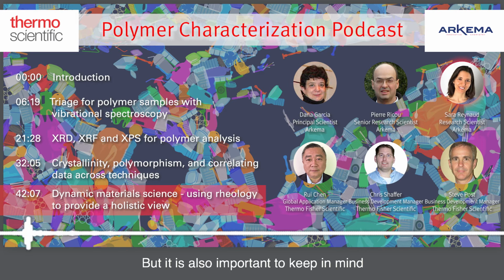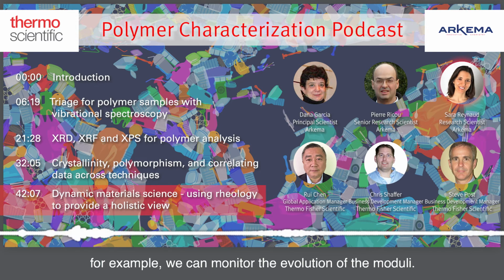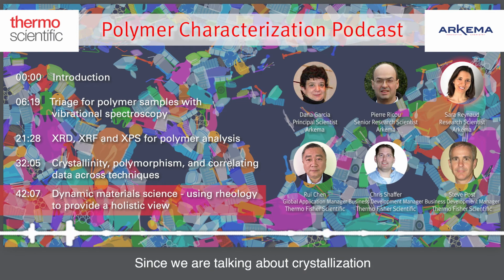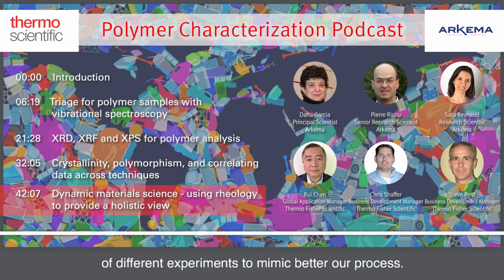But it is also important to keep in mind that rheology is not simply a technique for measuring viscosity. It can be much more complex than that. I would say that dynamic oscillatory shear testing is what gives us the most comprehensive information about the polymer at the molecular level. During a small angle oscillatory experiment, for example, we can monitor the evolution of the moduli. Since we're talking about crystallization in particular, we can measure the liquid-solid transition, or the gel point, or simply follow the nucleation and growth process during an isothermal crystallization experiment, and much more. We can really think about a variety of different experiments to better mimic our process.